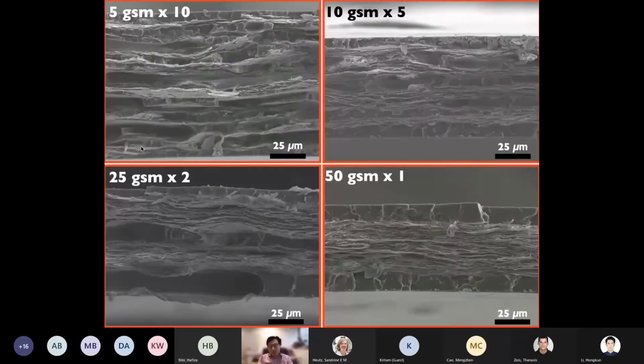And here's the microstructure that you can see. In the context of just looking at the bottom right corner there, you have 50 grams per square meter. So you actually see your polylactic acid sandwiching your nanopaper inside. Again, if you have two pieces of 25 grams per square meter nanopaper, you see the nanopaper with the polymer matrix, and you can extend this to 5 sheets of the nanopaper or 10 sheets of the nanopaper there. So the nanopaper gets thinner and thinner, but the overall mass of cellulose per unit area of composite stays the same at 50 grams per square meter.